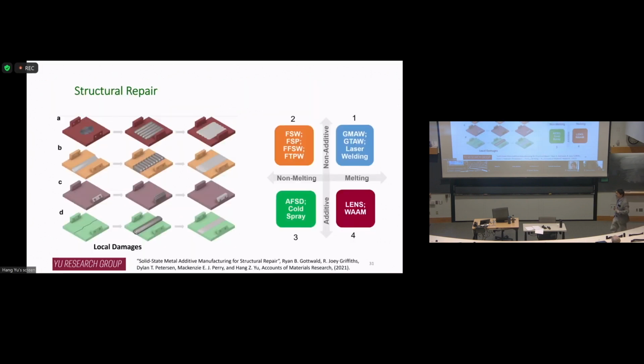Another application is repair. When you have large metal components, you can always have local damage like surface divots, trenches, missing features or cracks, right? What do you do with them? You want to repair them, rather than just throw away a big component with local damage. How to repair that? In this case, we want to do structural repair as opposed to so-called cosmetic repair. Structural repair means I want to repair the geometry, and at the same time also get good mechanical properties.